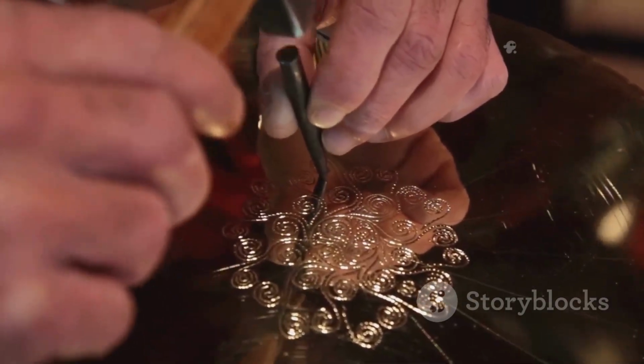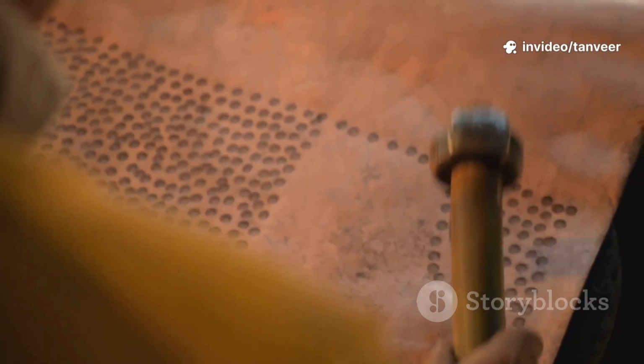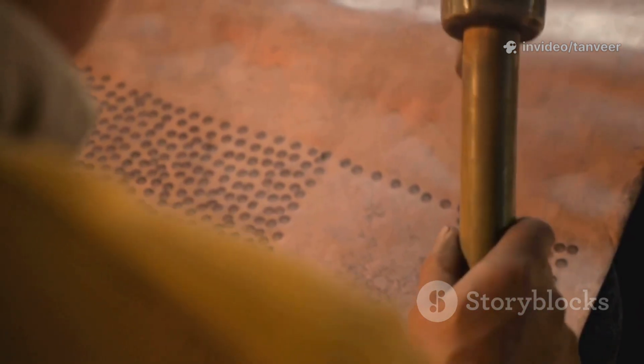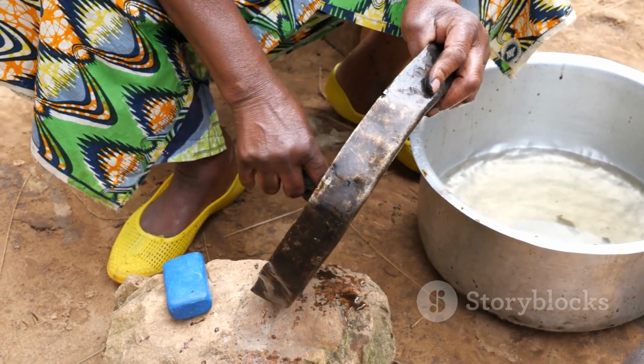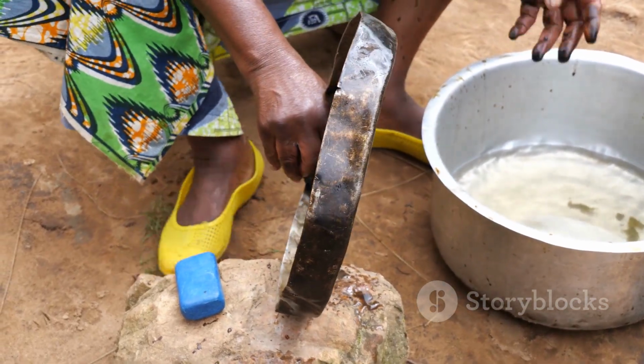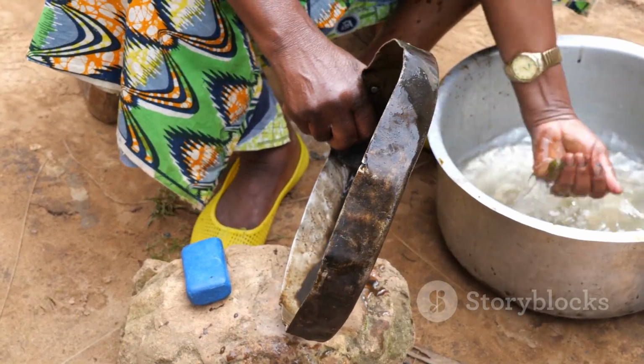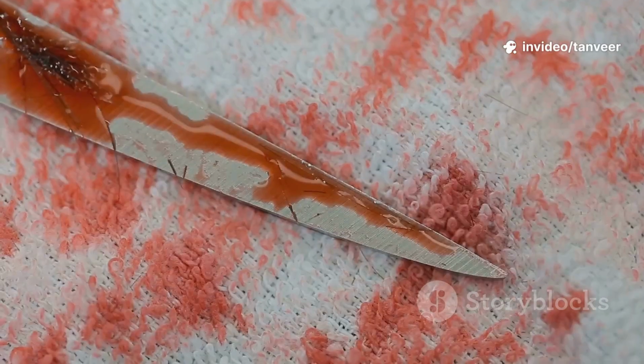Now the magic: etching in ferric chloride. The acid darkens the 1084 steel, but leaves the copper bright, revealing the dramatic pattern. A coffee bath deepens the contrast, making the copper veins pop against the dark steel. After neutralizing and cleaning, the pattern, like fiery fingerprints, emerges in full glory. The 5160 core forms a crisp silver edge.